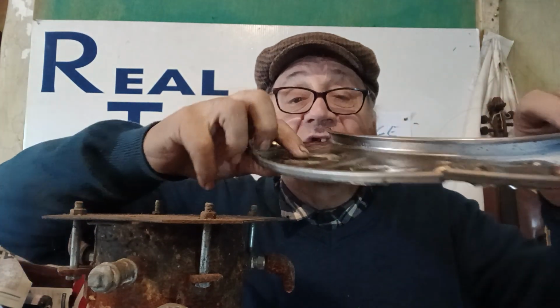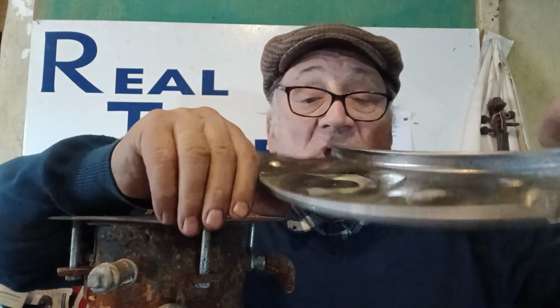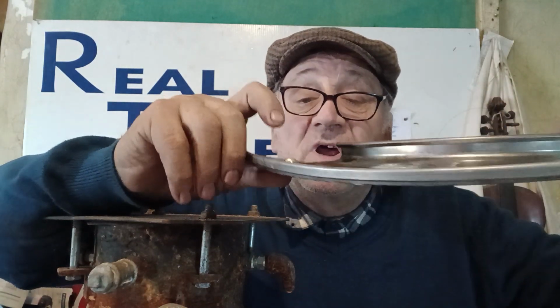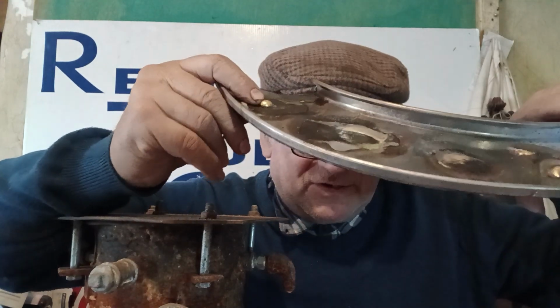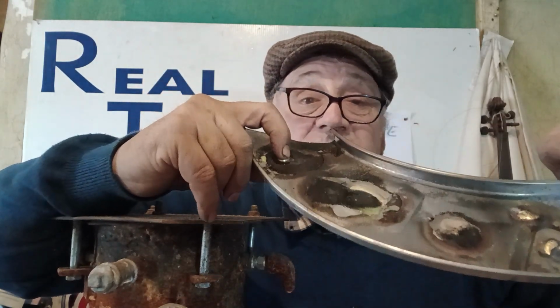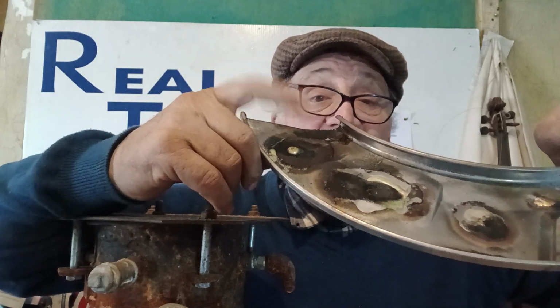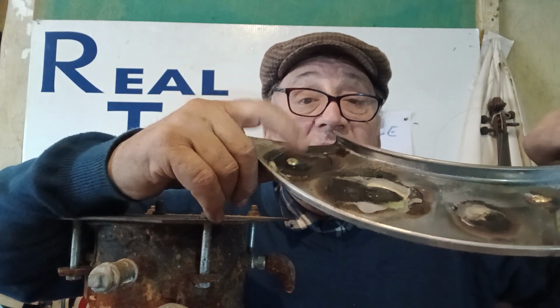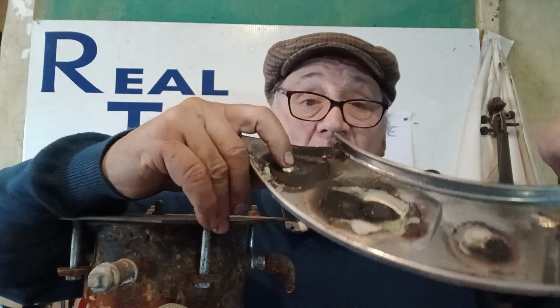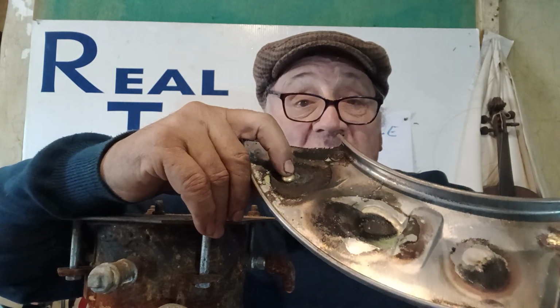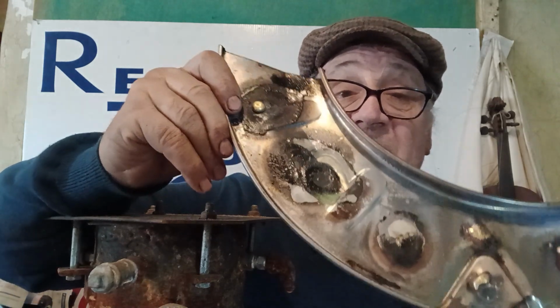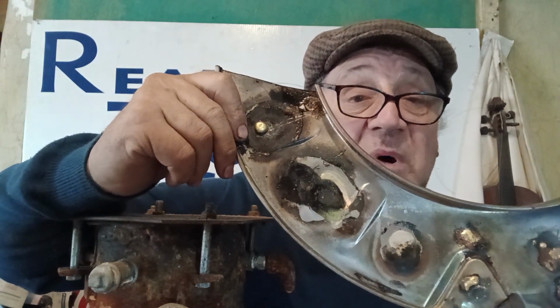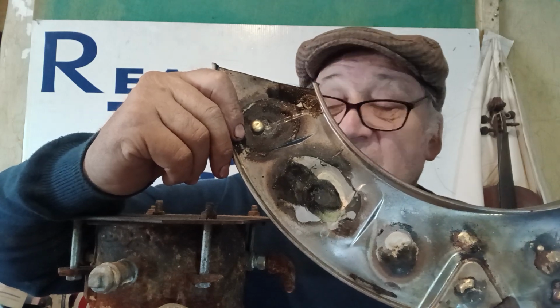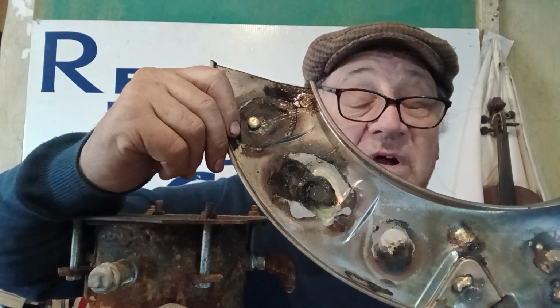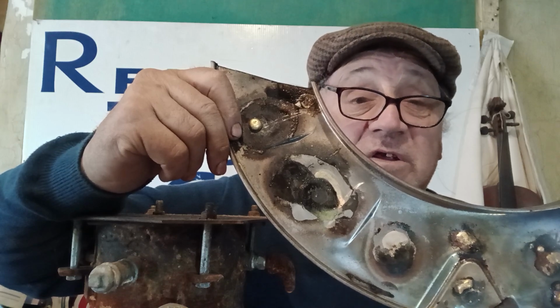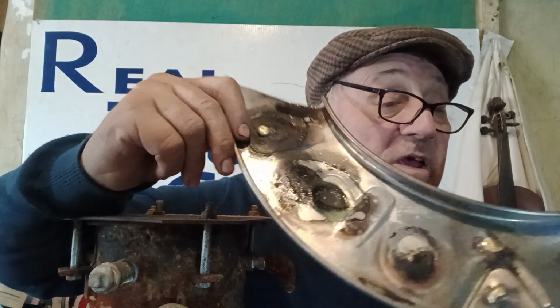Now, here's an example where it didn't work. It ran off it like a bubble. It's difficult. Here's an example where it did stick. Look at that, it stuck to it tight, but it's a lump, because I couldn't get the temperature of this high enough without melting this here with oxypropane. In all cases, what I'm showing you here is oxypropane. Propane uses more oxygen, but you only have to buy the oxygen. You have it simple. You can buy the propane anywhere. It works good enough in most cases, except for certain delicate cases and jewellery where acetylene is still the king.